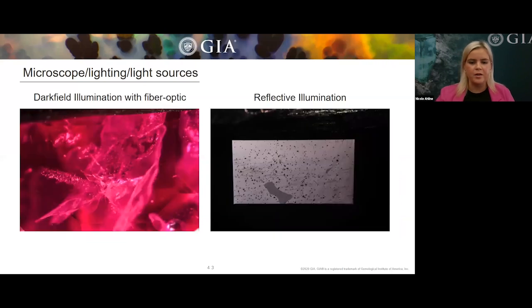And another example here, so on the left, we have a ruby again with dark field illumination with fiber optic, and we can see that there's numerous filled fissures in it. So this stone has seen high heat treatment. And when we only use reflective illumination on that same area, there's actually a filled cavity there. And so that filled cavity, we do count it as a treatment and it will be reported on your report, but that wouldn't be found without the use of that reflective illumination and lighting technique.